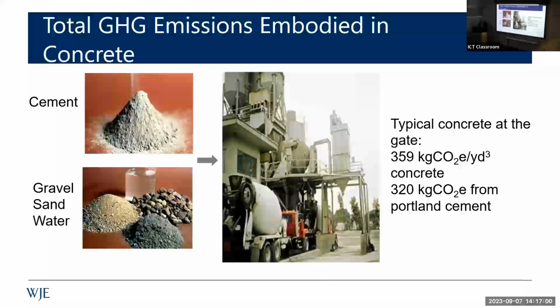We take that cement, we combine it with gravel, sand, water, admixtures, and typically we're going to end up on average in the US with some SCMs, about 359 kilograms CO2 equivalent per cubic yard. And people hate the mixing of the units here. I mean, it's not often you're going to see kilograms per cubic yard, right? But when we're talking about CO2, CO2 is always reported in kilograms equivalent. That's how you report it. So you never talk about pounds of CO2. That's just because of the ISO standards. So get used to that unit for whatever you apply it to. And out of that 360 roughly, 320 kilograms CO2 equivalent is from the cement.